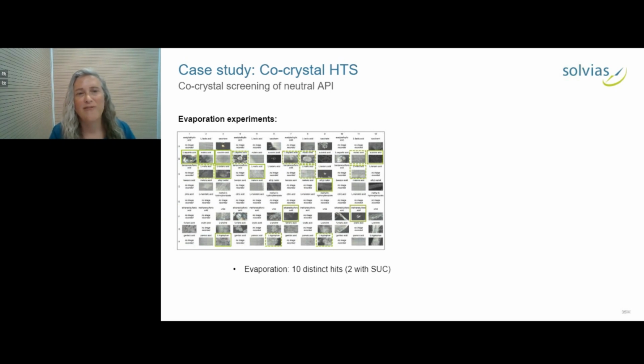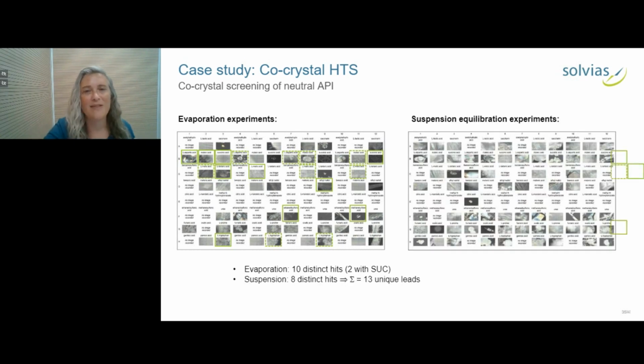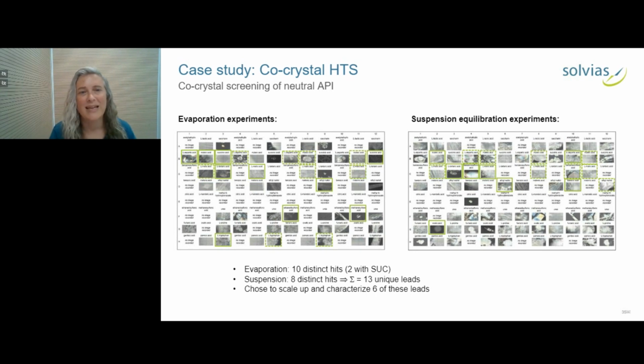And from evaporation, we found 10 distinct hits, 2 different ones with succinic acid. And in this picture, the solid green lines represent unique hits, and the dotted lines are just cases, other wells in which those same hits were also observed, because we had 4 different conditions for each potential co-crystal former. And then we did similarly for the suspension equilibration, and we found 8 distinct hits in that plate. And comparing the 2 plates together, because some were found in both, we had 13 unique leads. And then together with the customer, we decided to scale up and characterize 6 of these leads.